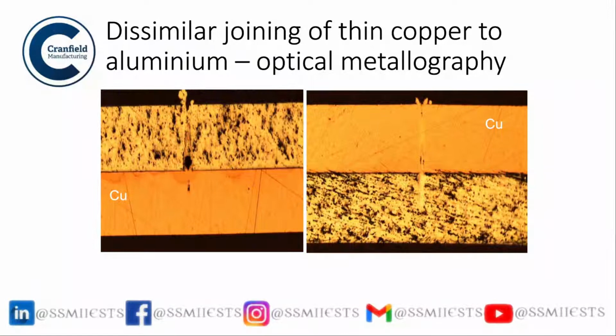So aluminium on top and copper on top, and as you can clearly see, the weld formation is much better when copper is on the top. The reason being, in the configuration when aluminium is on the top, the joint formation was not contributed to by copper much at all. But here, the copper penetrates well within the aluminium when it is being irradiated.